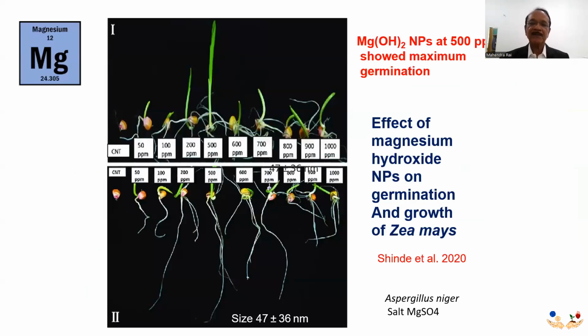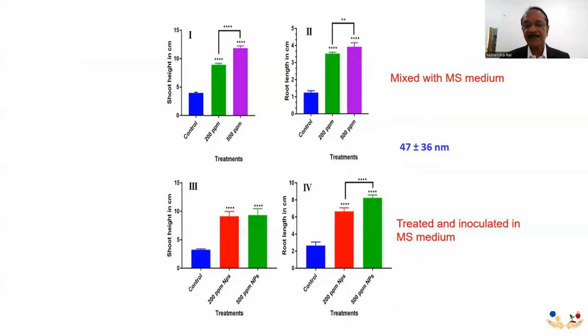A simple experiment was performed in my laboratory, and we used maize seeds and treated them with magnesium hydroxide nanoparticles. We selected magnesium because magnesium forms the phytol ring. It is one of the important elements of the phytol ring, which is responsible for chlorophyll. So different concentrations were applied, and it was found that 500 ppm is most effective on germination of maize seeds as well as their growth. These nanoparticles were synthesized by Aspergillus niger.